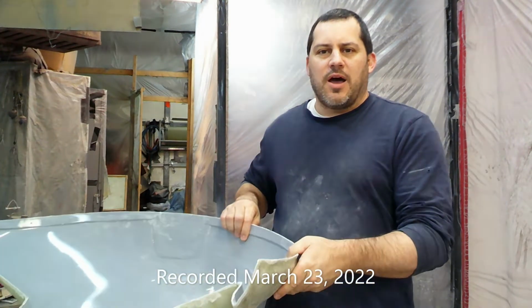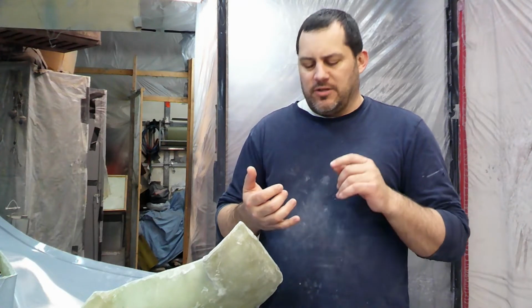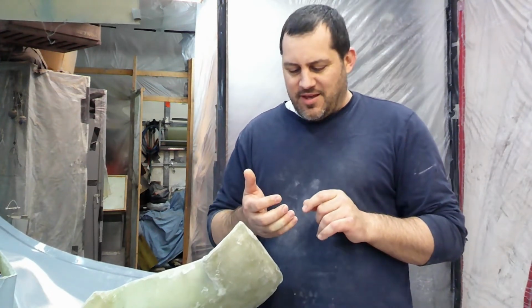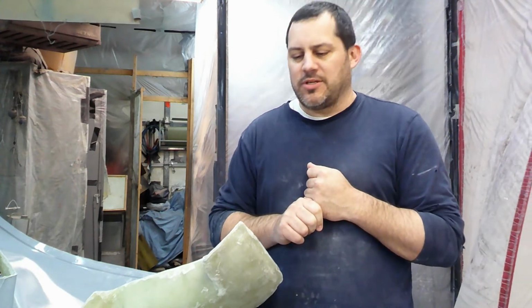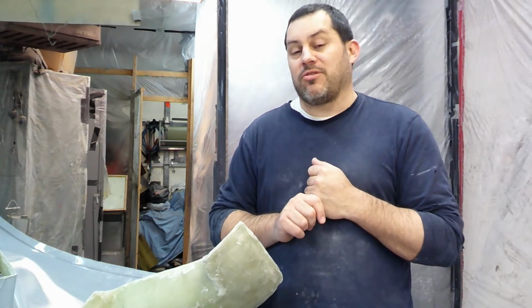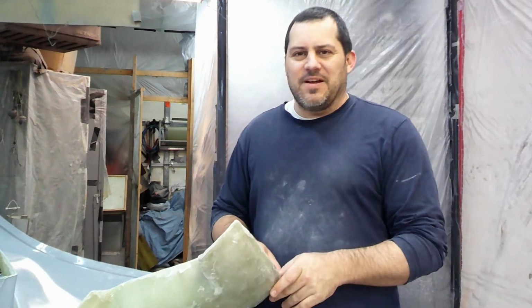If you watched parts 1 through 4 of the videos making the nose bowl molds for Earl's Buttercup, then what you saw was the process of making this mold here, from taking the plug, once we had the wax and the PVA on it, to applying the gel coat. I apologize for the heater, trying to get a little bit of work done here Wednesday evening. So we applied the gel coat, first and second coats. We applied the cloth fabric reinforcement, 4 ounce, 6 ounce, 10 ounce, 2 layers of mat, and then a cap of 10 ounce. And that was, I believe, part 3. Part 4, you watch me fight ferociously to get this thing off of the plug, and the results.